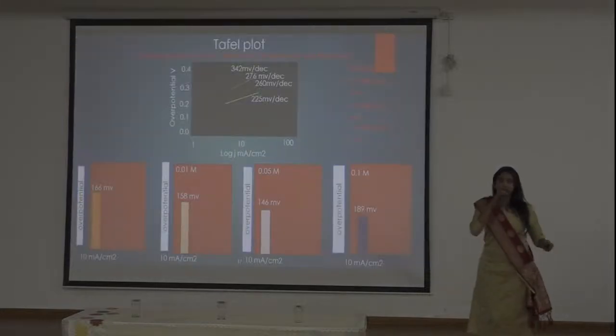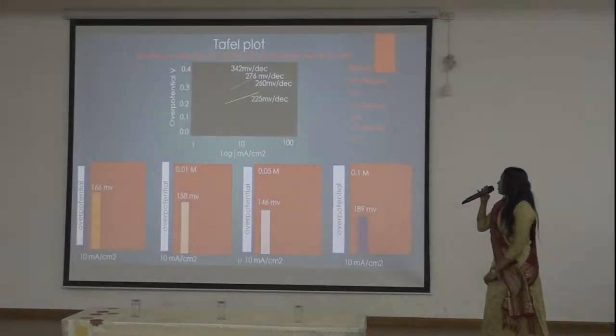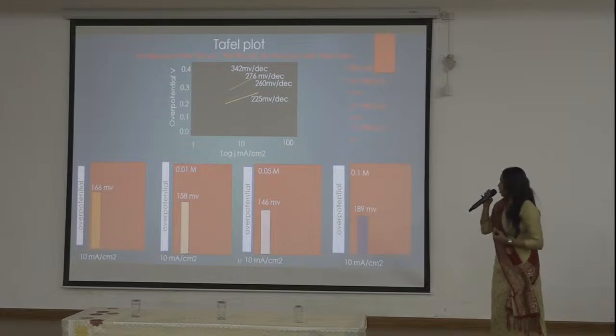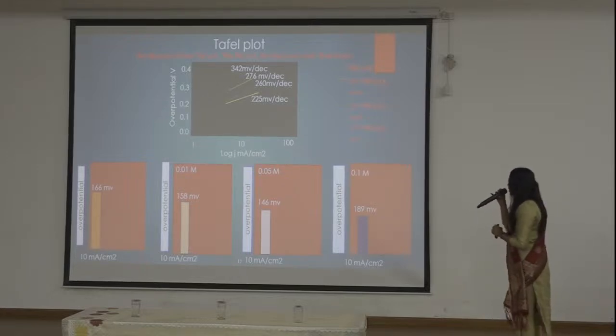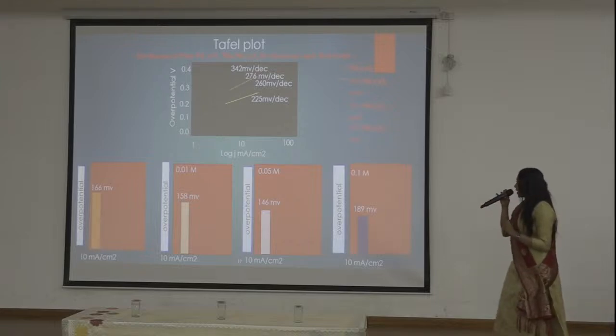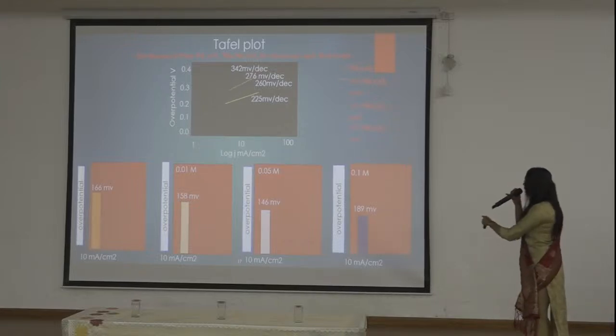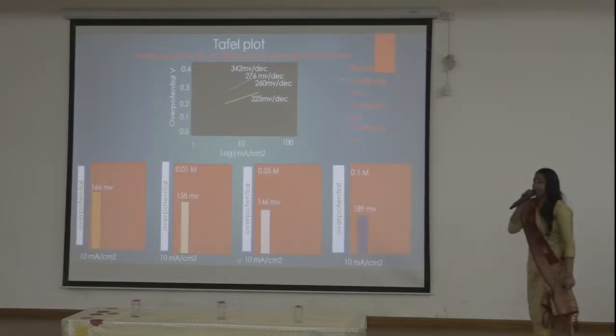Next slide. So I have calculated the Tafel plot. By considering LSV and Tafel plot, I have calculated the over potential. I get a good result in 0.1 molarity ratio of manganese doped nickel cobalt oxide, which is 189 millivolt at 10 current density.